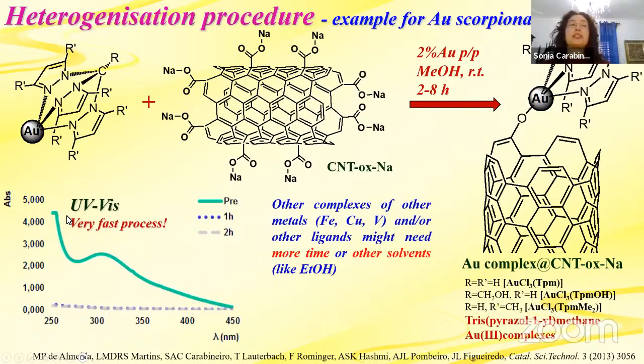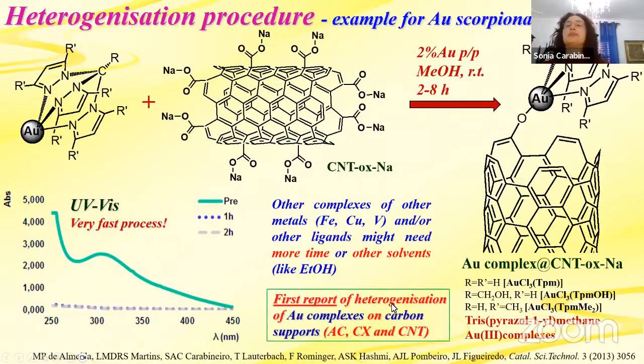And you see, it's a very fast process because we did ultraviolet visible spectrometry just to check. And here is the solution before anchorage. So we have very large bands, above what would be measurable. But after 1 hour with the carbon material, the complex is anchored on the surface. So if we do an ultraviolet visible of the supernatant liquid, we see there is almost nothing there. After 1 hour and 2 hours, there is almost nothing. So the gold complex was totally anchored on the support.